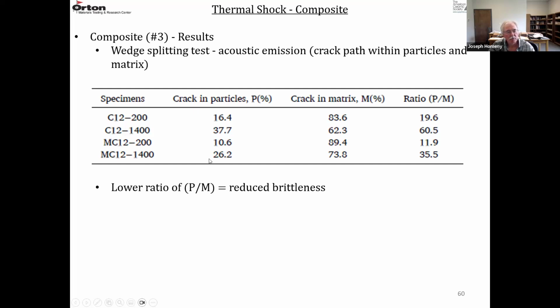And then the MC12, the finer material, you're starting out with a 10% relative to 16, so there's less coarse particles fracturing in the finer material and more matrix fracturing. This is 89 relative to 83. And then at the higher temperature, 1400 degrees C coking, about 26% of the particles are fracturing, but it's still less than in the coarse material. And then 73% of the fractures are in the matrix, which is higher than in the coarser material.